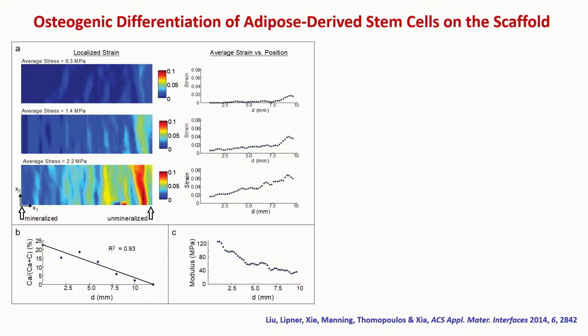Depending on the average stress we applied, you can see this is a region with a higher level of mineral coating, and this region to the right has the least amount of mineral coating. So as you can see, in this case, at a high stress level, the strain is not going to be uniform. You are going to see a gradient in terms of strain on the surface. That's also going to be reflected by the gradient of the mineral phase on the surface.